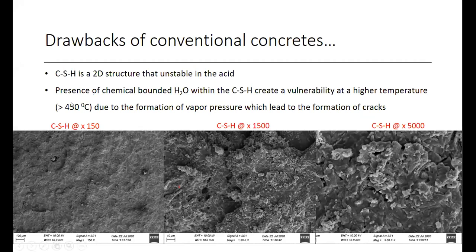This is basically a 2D structure, which is not very stable in acid, and which is amorphous. Because of that, it's very hard to detect with XRD techniques. We have to utilize other techniques to identify the C-S-H formation, like FTIR, NMR, and so on. And since this C-S-H gel is formed with calcium, silicon, and chemically bound H2O, it has a vulnerability at higher temperature. At more than 450 degrees, it has a tendency to deform or decompose the C-S-H gel back to H2O.